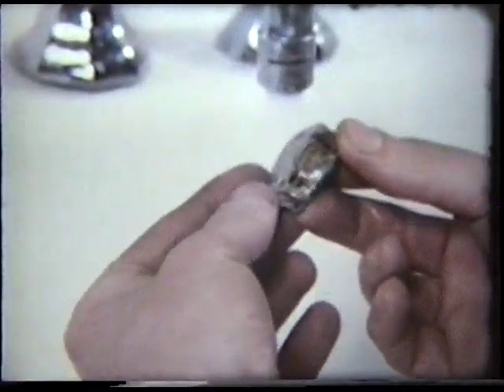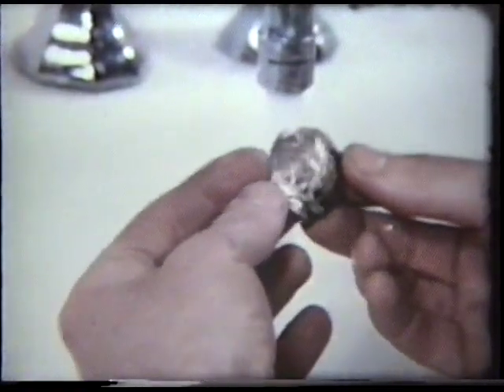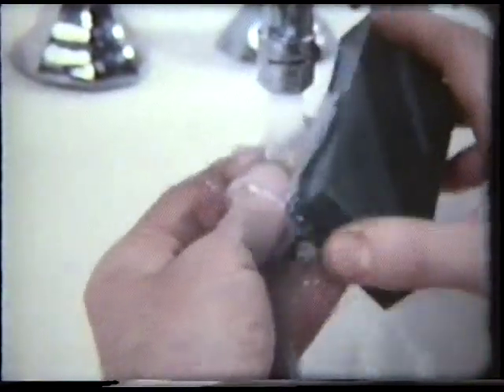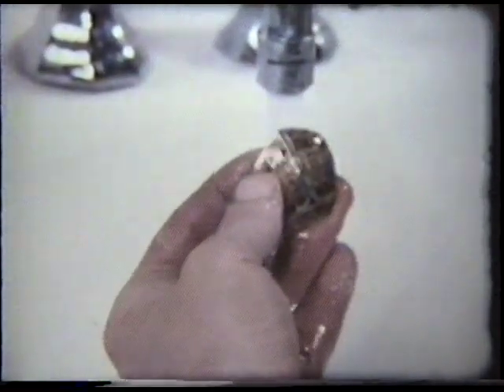To bring the surface to the height of the cloisons, the piece is rubbed with a carborundum stone under running water. This grinds away the high spots and leaves the surface roughened but uniform in thickness. After it has been stoned, it is cleaned and refired to regain the glossy surface.